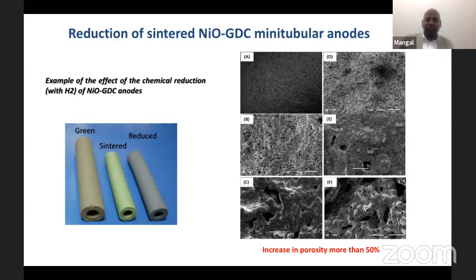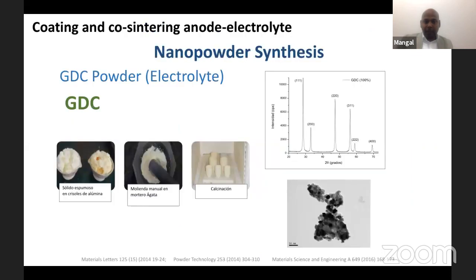So we reduce only the nickel oxide to create porosity, microporosity. Obviously, when we fabricate tubes, we also evaporate the polymers, so you also get macro pores. So both micro and macro pores are present in the tubes. These tubes act as an anode for our fuel cells. After fabrication, sintering and reduction of these anode tubes, we started coating electrolyte powder. Of course, for the electrolyte powders also, we adopted the combustion synthesis.